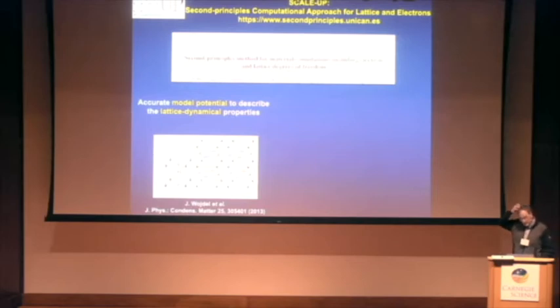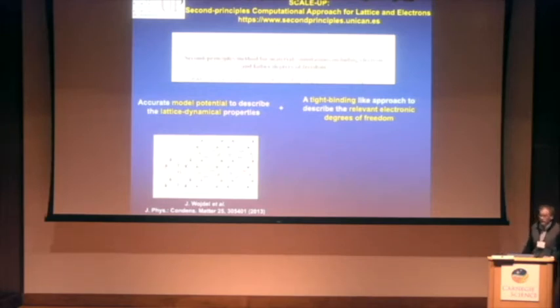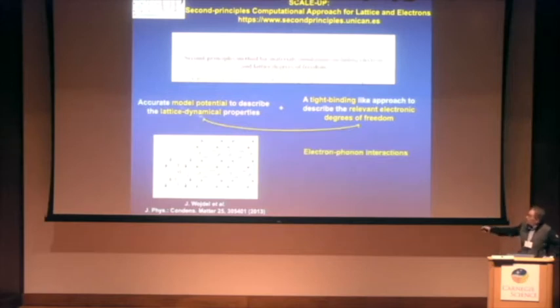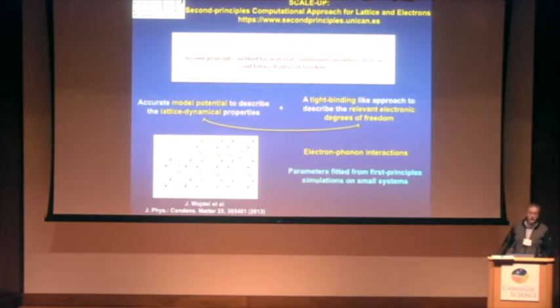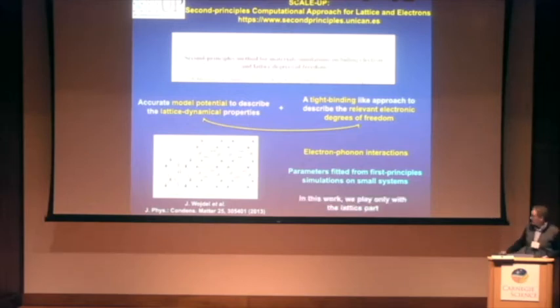So just a bird's-eye overview of the method. We are combining an accurate model potential to describe the lattice dynamics, and we include here all the possible modes of the materials, ferroelectric, antiferrodistortive, whatever, all of them. And on top of that, we have a tight binding-like approach to describe the relevant electronic degrees of freedom, and we have the cross-talking between the lattice degrees of freedom and the electronic degrees of freedom. So we have all kind of electron-phonon interactions. So we call it second principles because we don't have any input from the experiment. So all the parameters are taken from first principle simulations on smaller systems. And despite everything has already implemented, I have to say that in this work, we play only with the lattice part. So all our systems are insulating, and therefore, we are not using the electronic capabilities in this study.